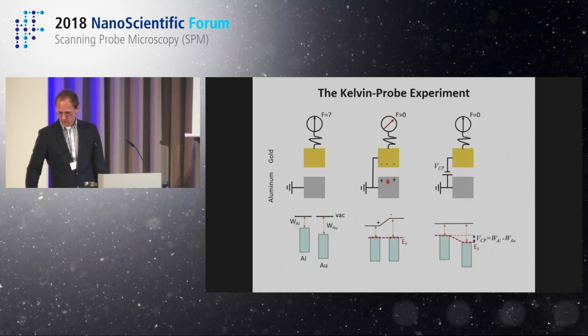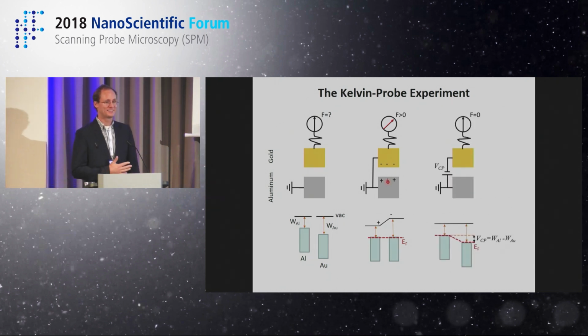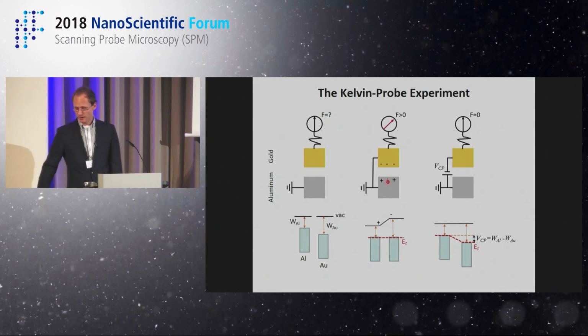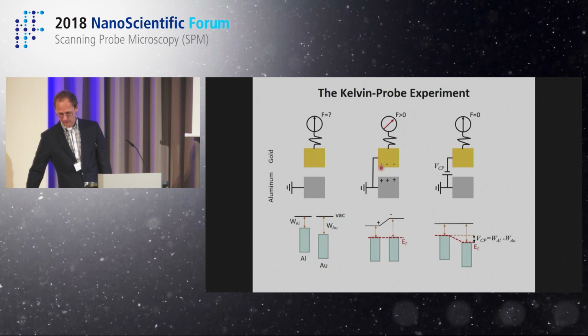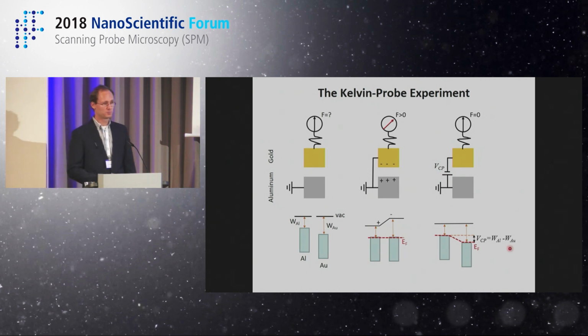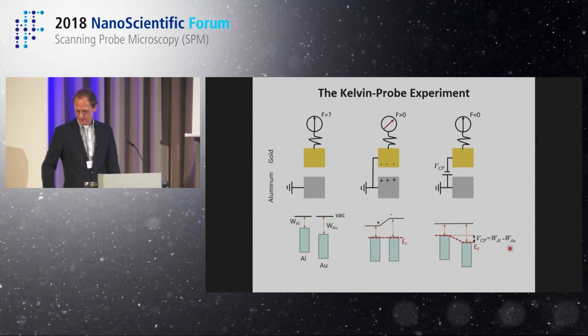The trick is then to apply a potential that is exactly large enough that the force is exactly zero. That nullifies this electrostatic force due to the differences in work function, and that is what you're doing here. And then you know exactly that the potential that you apply is equal to the difference in the work function between these two metals. Right? That's the macroscopic effect. The nice thing is that this effect you can exactly translate to the AFM, to the nanoscale.